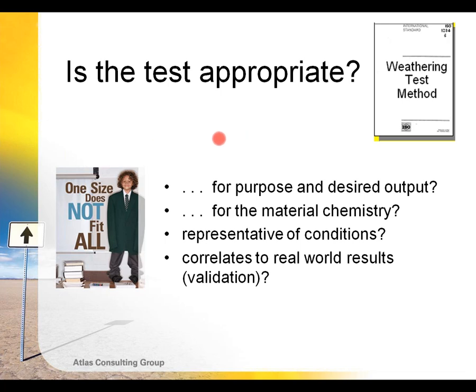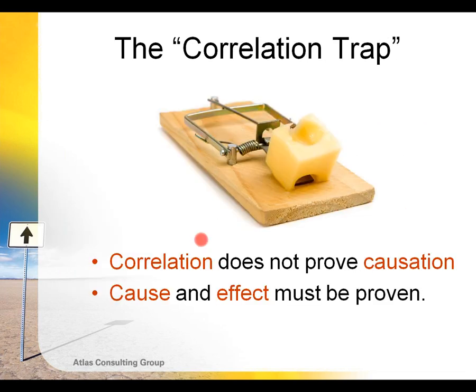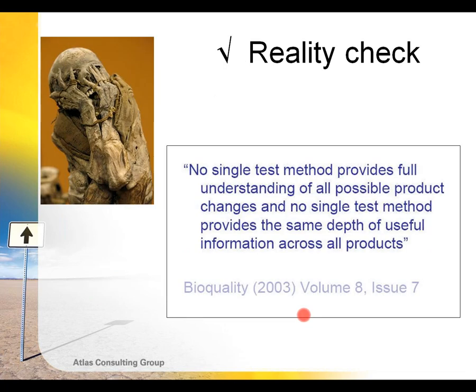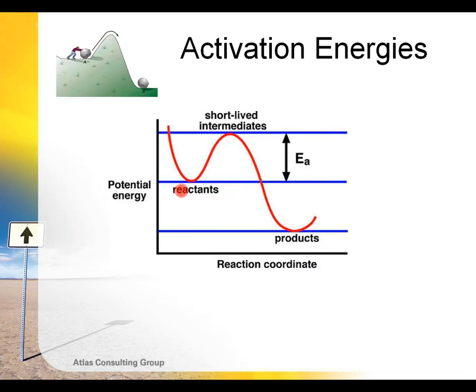And just one cautionary note: most of the applicable international weathering standards are very inadequate for predicting performance in any particular climate. None of them really do that. So you must always look at standards, but understand whether or not they are suitable for the intended application and the nature of the product and its specific material chemistry. And also, just because you get a change of property in a test does not prove correlation. In other words, it does not prove cause and effect. Different products can yellow from the effects of temperature or UV solar radiation, so cause and effect must be proven. And no single test is going to tell you everything you need to know. You need to do a number of different tests.